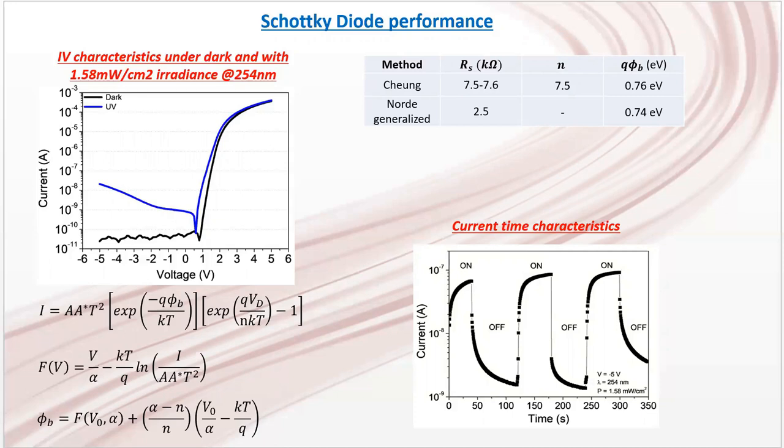In terms of sensing performance, the metrics I'll discuss a little bit later, but you can see here is the rise time and the decay time of our photodetector. We can see that both the rise time and the decay time are relatively similar at 20 seconds each.